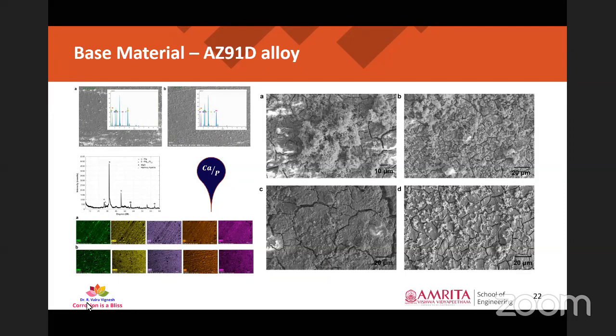Added to that, previous studies have given us the idea that if hydroxyapatite is formed over the implant material, that will support bone growth and implant bone integration. Why? Because it is the natural constituent compound of the human bone. And we have done XRD analysis to confirm if this phase is particularly hydroxyapatite based. Yes, of course. The XRD results also confirm that the specimen after a period of 7 days exhibited the formation of calcium hydroxyapatite and calcium magnesium based hydroxyapatite crystals too.